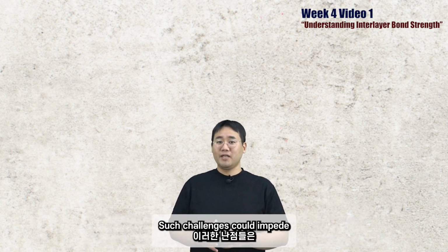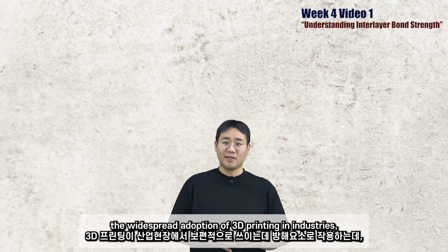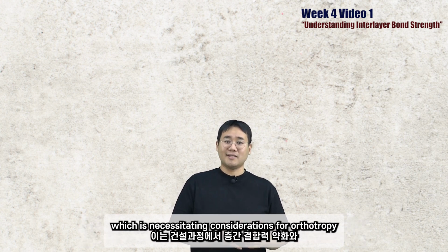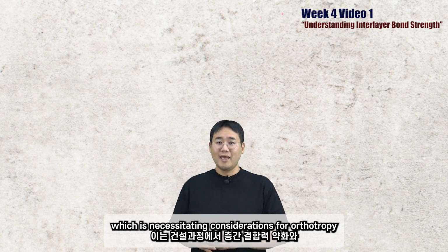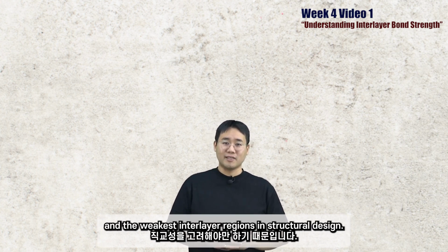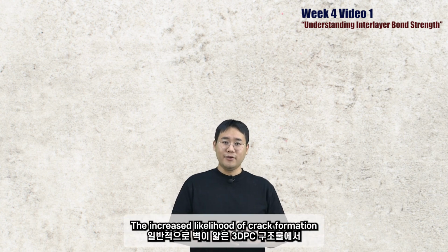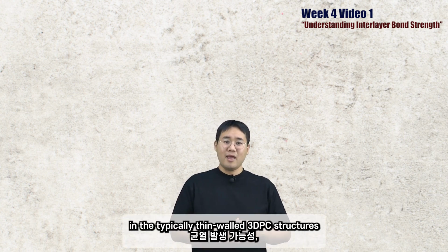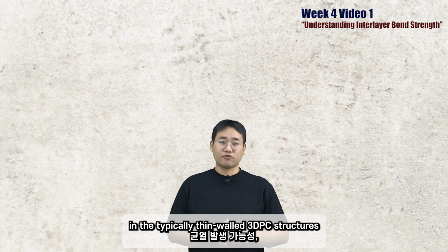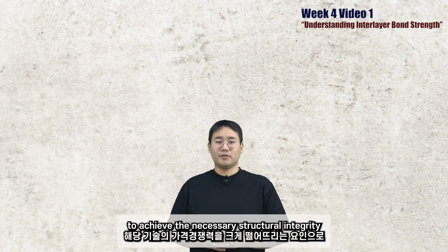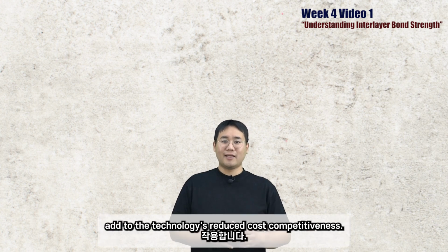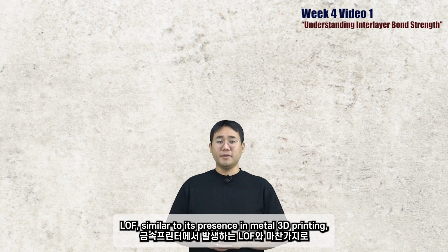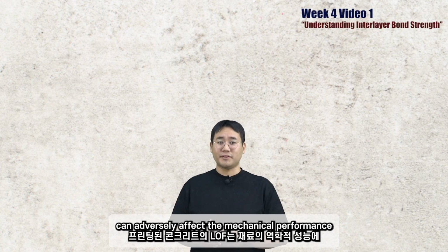Such challenges could impede the widespread adoption of 3D concrete printing in industry, necessitating consideration for orthotropy and the weakest interlayer regions in structural design. The increased likelihood of crack formation in the typically thin-walled 3D printed concrete structures, and the need for reinforcement to achieve the necessary structural integrity, add to the technology's reduced cost competitiveness. Lack of fusion, similar to its presence in metal 3D printing, can adversely affect the mechanical performance of printed concrete structures.